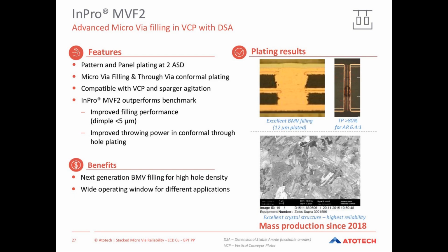InPro MVF2. This is a process which works with insoluble anodes and copper oxide replenishment. Applicable in vertical conveyor lines, but also in vertical hoist lines. And this new development has a big advantage that you can also run the process with higher acid concentrations, around 100 milliliter per liter, which gives you the advantage to have an unmatched surface uniformity at the end, and also get a really good throw in through holes.